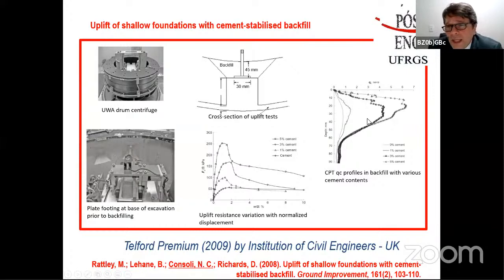Here are the CPT tests that we have carried out inside the centrifuge to show how this backfill strength was, here in the beginning without any cement, here with 1% of cement, with 3% and with 5% of cement. Right below here, we had some soft soils. It shows that in the end, for the soft soil, it also comes to a unique result. But here, the improvement is quite massive.